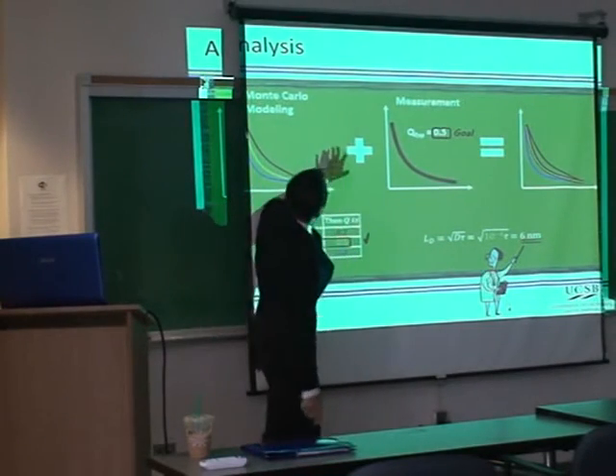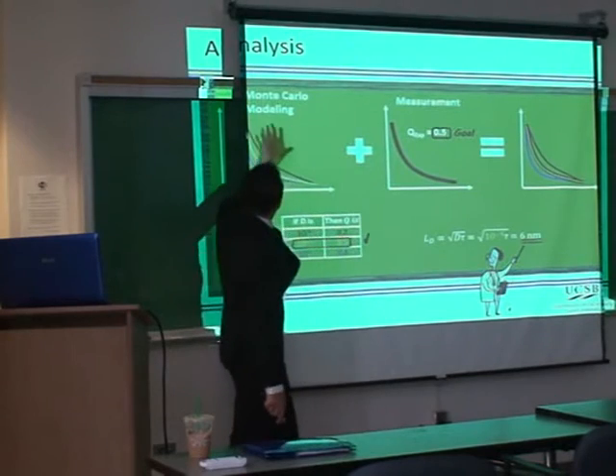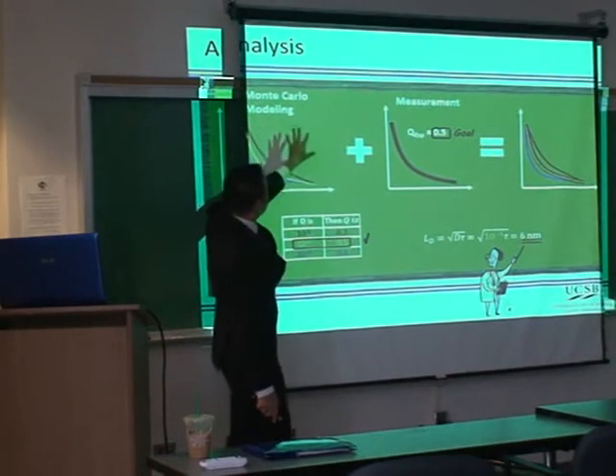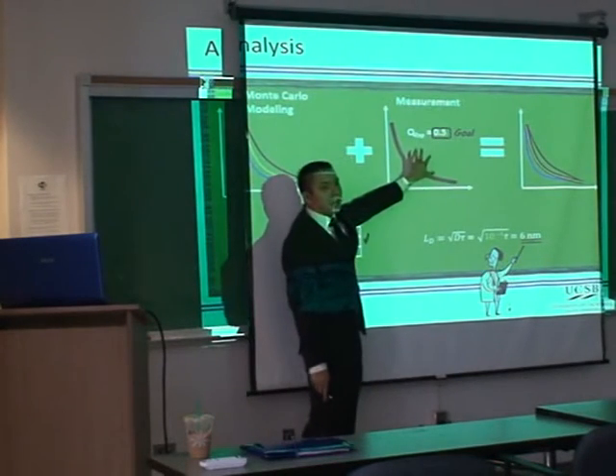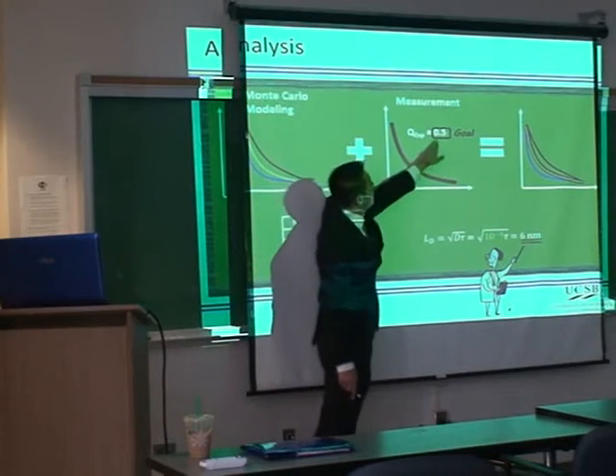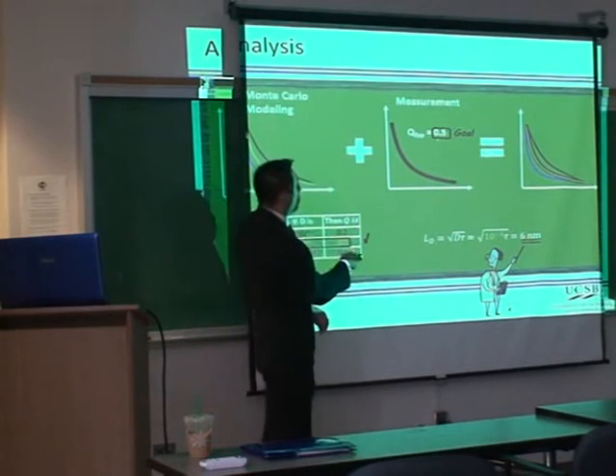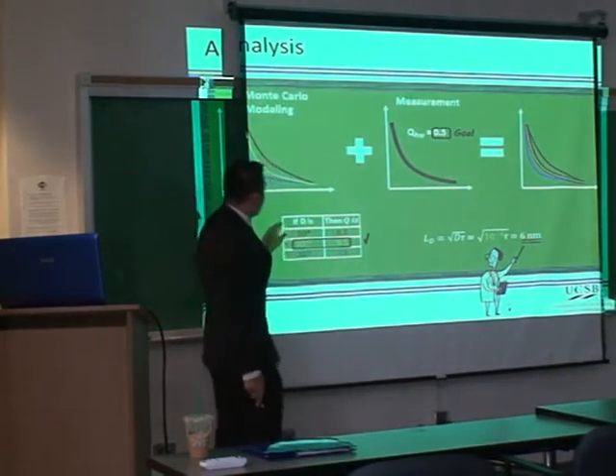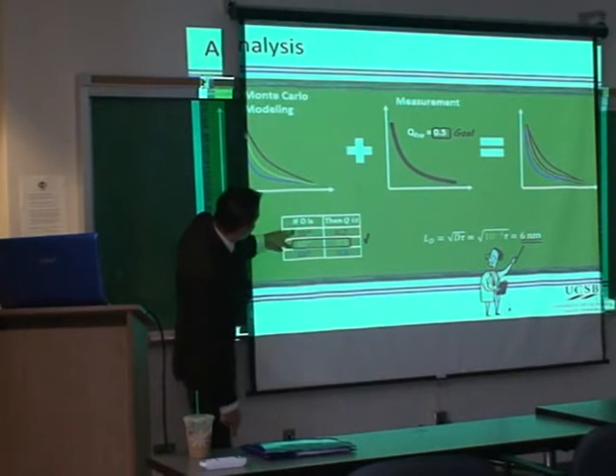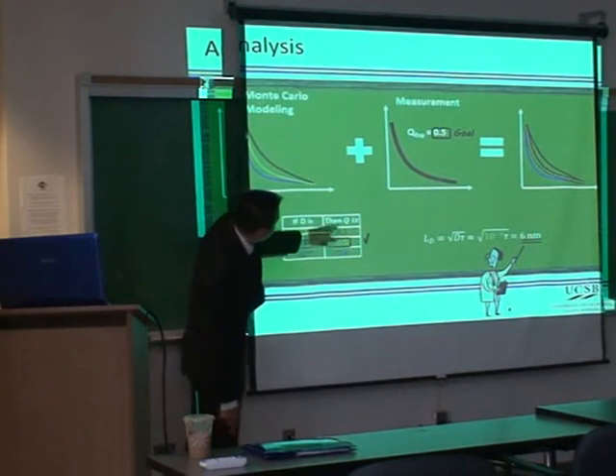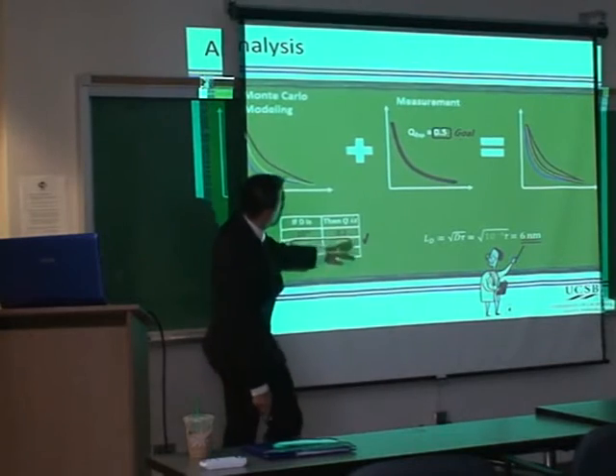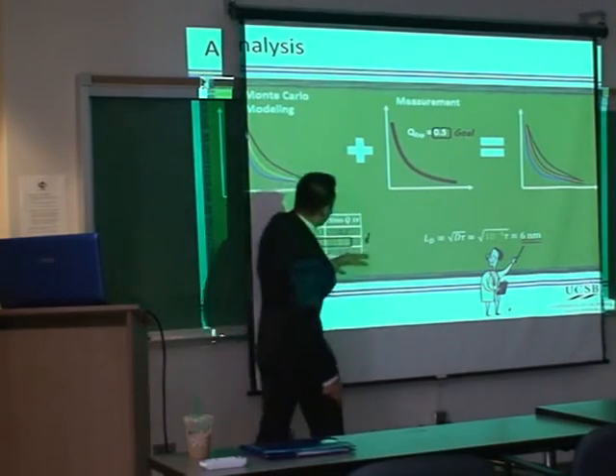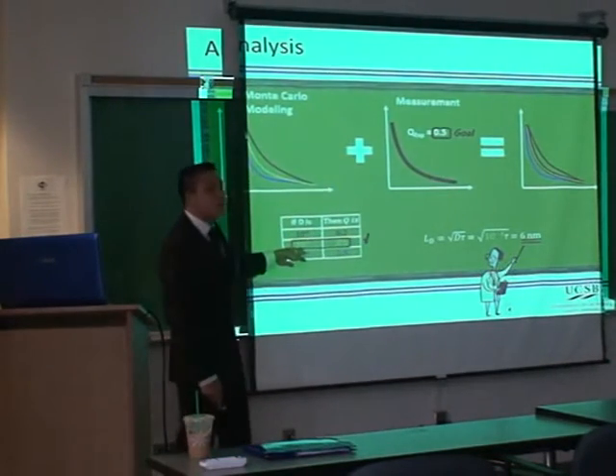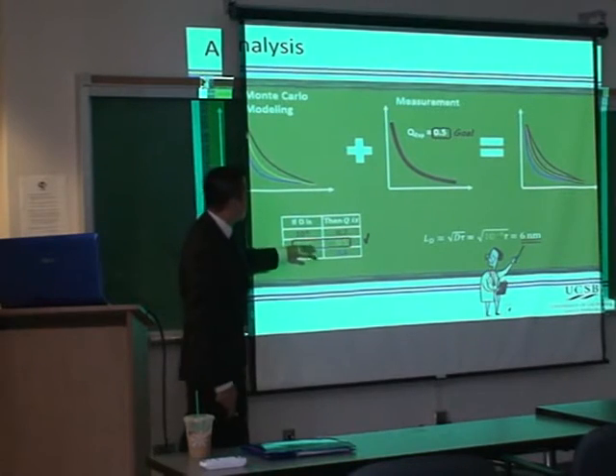So finally, we come back to the little guy in the computer, and what he wants to do is compare the measurement with the Monte Carlo method. So let's say, just for example, that you do the measurement and you get a quenching efficiency of 0.5. So that is the goal to look for. What you then do with the Monte Carlo is that you simulate for different diffusion coefficients what the quench efficiency would be. And then you match the two. So you see that 0.5 matches 0.5 here, which corresponds to a diffusion coefficient of 10 to the negative 4.